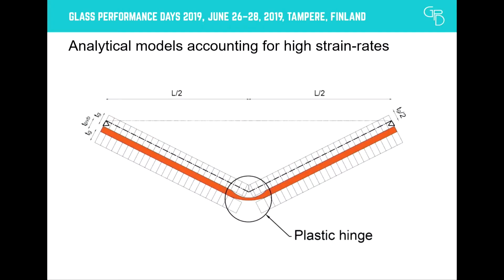A similar approach has also been performed in some other publications that refer to the post-fracture response of laminated glass beams with SGP, which is a stiffer interlayer. So the approach we're trying to introduce here is to say that due to the high strain rates, the stiffer response of the PVB will be similar to the experimentally observed result of laminated glass beams that have a stiffer interlayer. So once the moment capacity in stage 4 has been exceeded, a plastic hinge will form. If it's a simply supported beam, this will result in a collapse mechanism. For different boundary conditions, further plastic hinges may also form.